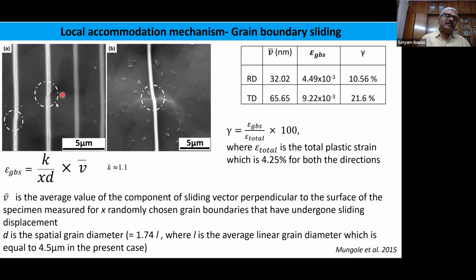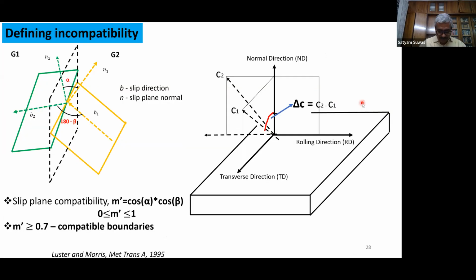So we could see here, in this region and this region, that there is clear evidence of grain boundary sliding in this case. The strain for grain boundary sliding was calculated by this method, which uses a geometrical factor given in this formula, and the strain for grain boundary sliding is given here. And this also has a difference, almost double for the case of TD compared to RD. So again, this further confirms that textures play an important role.